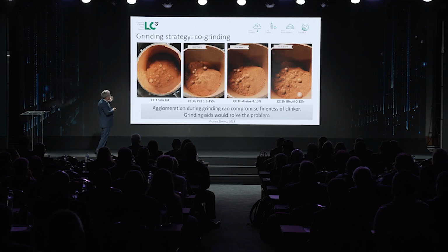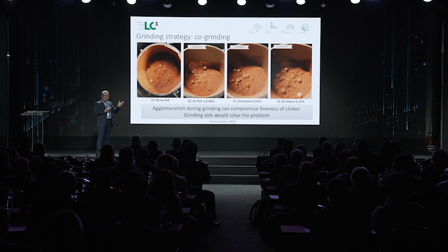But then we realized that it is as easy as using commercial normal grinding aids, especially of the types TIPA, TEPA. So TEA, TIPA, they work because the problem is that you create coatings on the steel balls. And these coatings prevent, and also on the walls of the mill, prevent the clinker grains to be further ground.